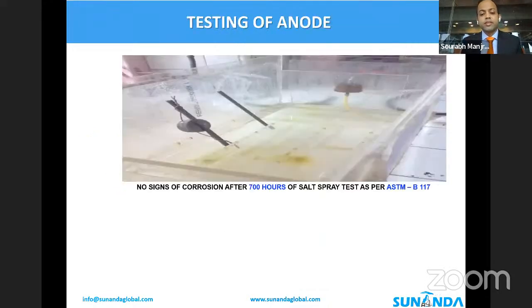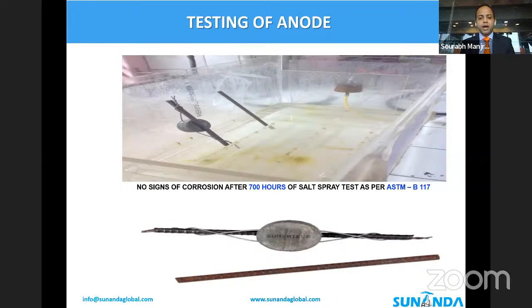There are numerous codal provisions for sacrificial anodes. So ASTM B418 is what I had mentioned earlier, is one of the codes. There are numerous codes for corrosion as well. So ASTM B117 is one of them, which we have conducted here. This is one rebar has a sacrificial anode connected, the other one does not. They are both subject to 700 hours of salt spray as per ASTM B117. And after that, the bar without the anode is completely corroded and the bar with the anode is as it is.